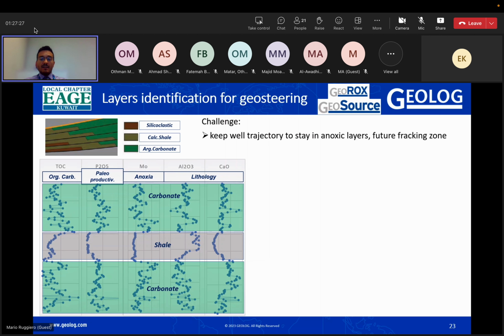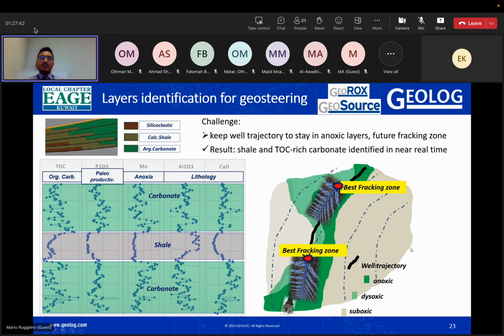Together with anoxic markers, in this case, the formation was rich in molybdenum, and also lithology markers such as aluminum and calcium, which are directly related to clays and carbonates. And this helped us in identifying the two better regions for fracking, so rich in organic matter and paleoproductivity proxy, which are, of course, the two carbonates.